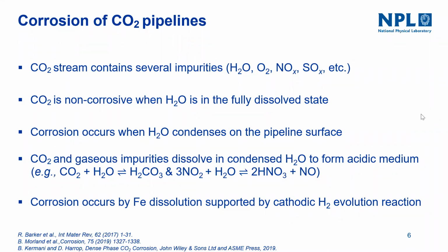So for example, here is a case of formation of carbonic acid and nitric acid. So the corrosion occurs by dissolution of iron supported by the cathodic hydrogen reaction. So what could be the reason for water to condense? One thing is the variation in the temperature and the pressure. So the solubility of H2O can decrease, and also the impurity content. If the impurities are more, the solubility of H2O in the CO2 decreases.